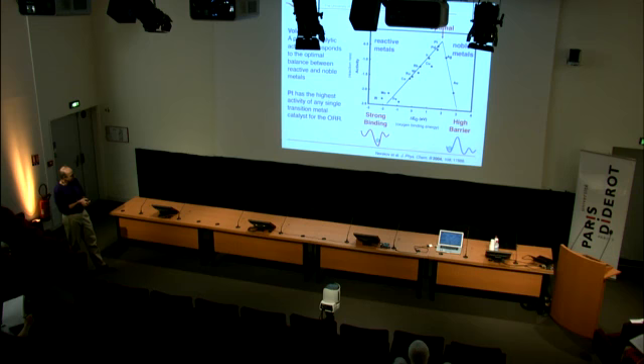Okay? And platinum is actually not an especially good catalyst for oxygen reduction. It's kinetically slow, it's easily poisoned by carbon monoxide, all the things we've heard about here for the last few days. But it's the best of these monometallic catalysts. So it's up near the top of this volcano, and it's because it has the best combination of being reactive, so it can break the dioxygen bond, but being sufficiently noble that it can release the products. That's why it's up at the top.